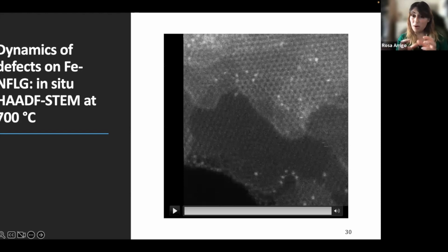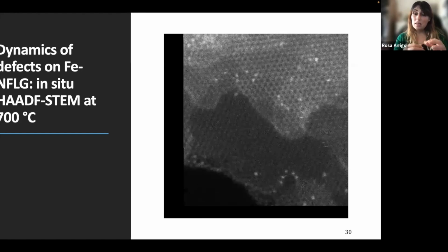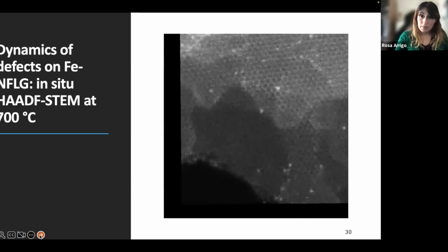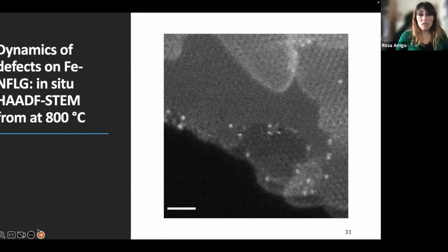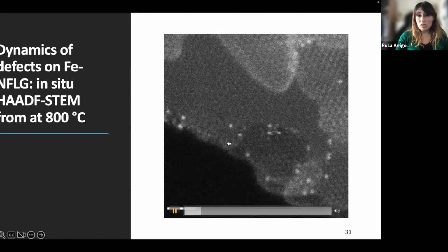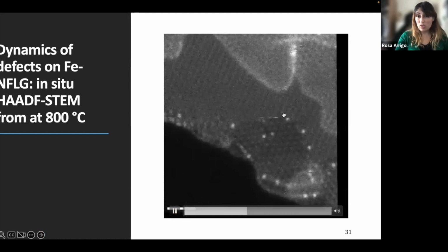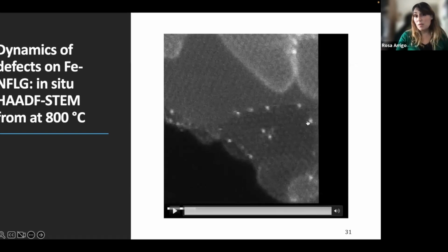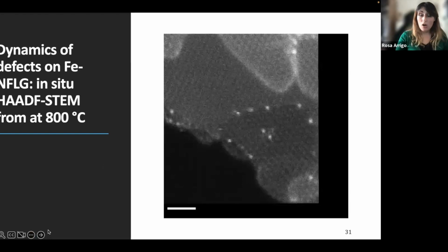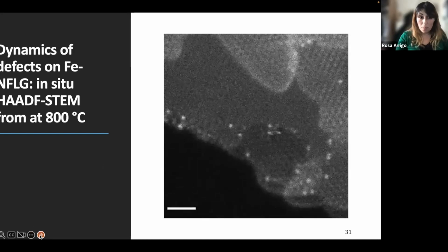graphite break, and there is a bond breaking and formation, and the iron moves from the edges toward the in-plane position. Yeah, and they are very mobile, and at some point even dinuclear species form. So one could imagine. Here you can see better how the graphitic edges are actually etched at 800 degrees C already, for example, and this will lead finally to the sintering of the iron species into metal particles.